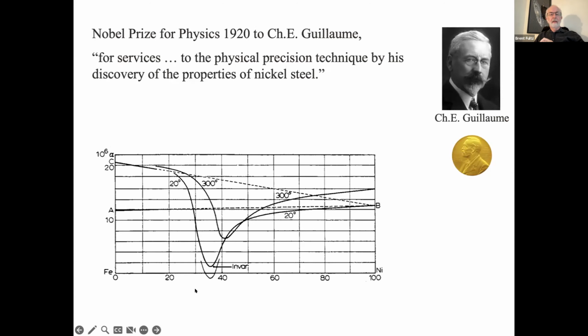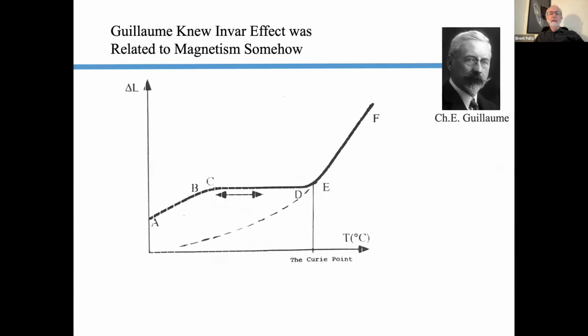He wasn't aware that there's phase transitions between BCC iron and FCC nickel. He just did these compositions and nevertheless discovered the anomalous thermal expansion. Notice how delicate it is. You have to be almost spot on in the composition, within 1% or so, not like other physical properties, the thermophysical properties like elastic constants, for example. Now, he knew there was something to do with magnetism here.